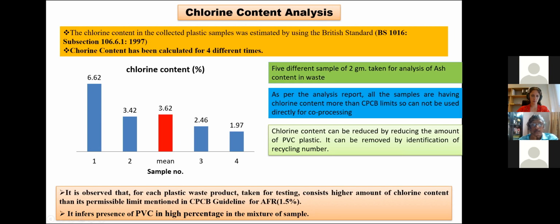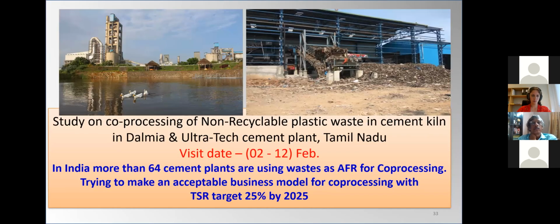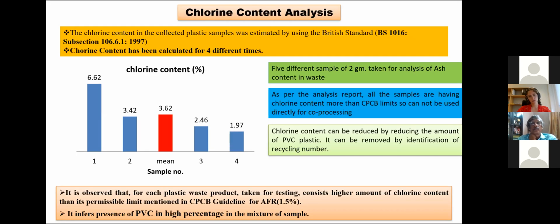And it is also found that all of the samples have varying chlorine content due to the heterogeneous structure. So it is recommended that we have to balance the PVC content, which is mostly due to the heavy amount of PVC. We have to balance the PVC content, and that can be done through segregating the PVC. After that, it can be used as an AFR.